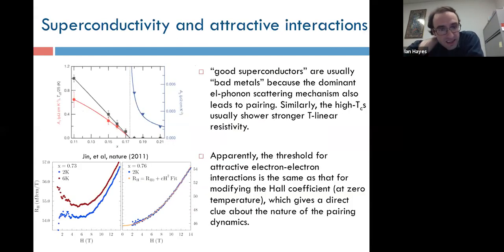The final thing I'd like to say about these results is that they provide potentially more information about the structure of the interaction that is responsible for superconductivity. So there's been a lot of work correlating the T-linear term in the resistivity with TC, and that's been seen in a lot of materials, cuprates as well as pnictides. And the analogy being that the stronger the scattering is, the stronger the interaction is, and therefore the stronger the attractive part of the interaction will be. The resistivity by itself doesn't allow you to factor out which part of the interaction, it doesn't give you any information about what part of the interaction is going to be attractive ultimately at low temperatures.